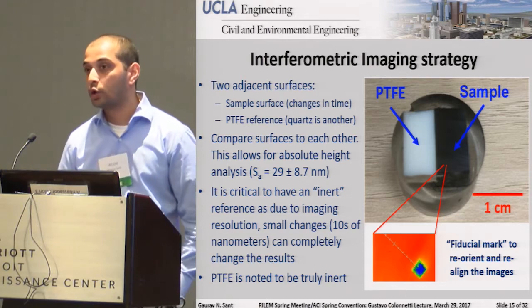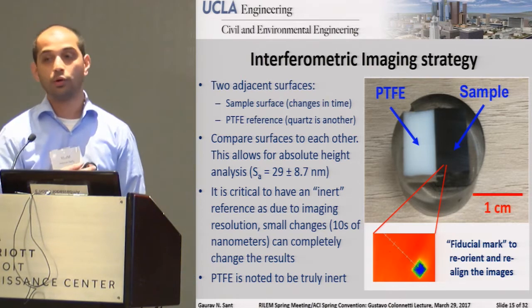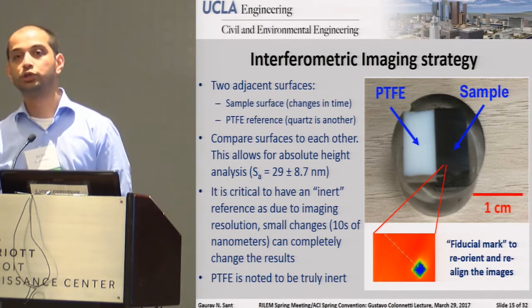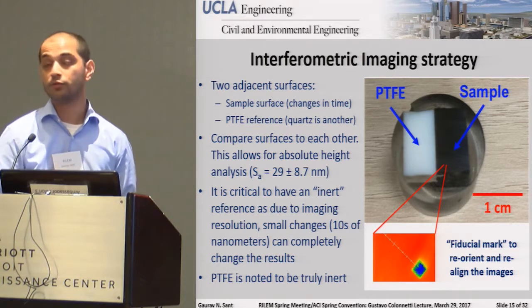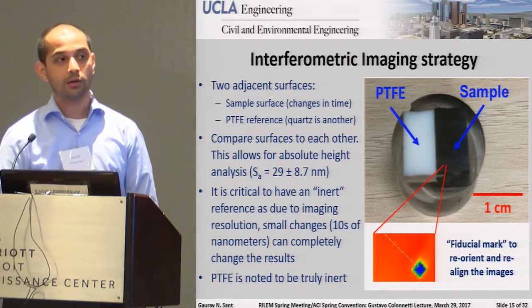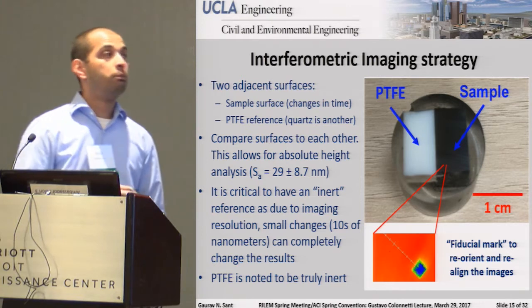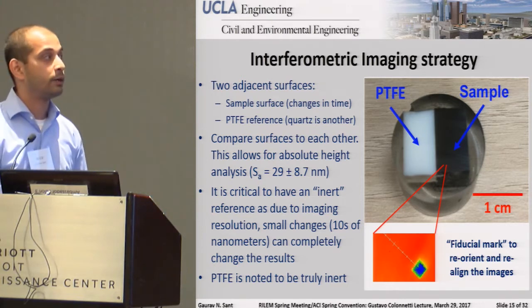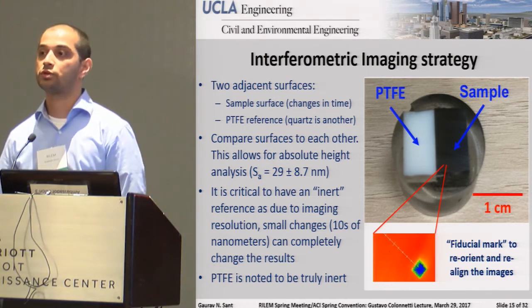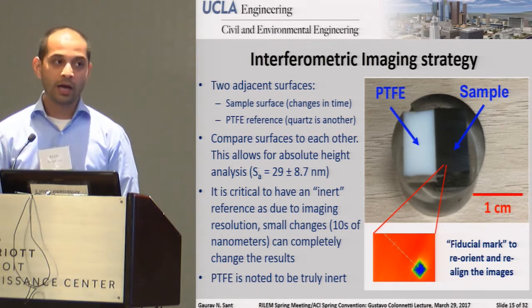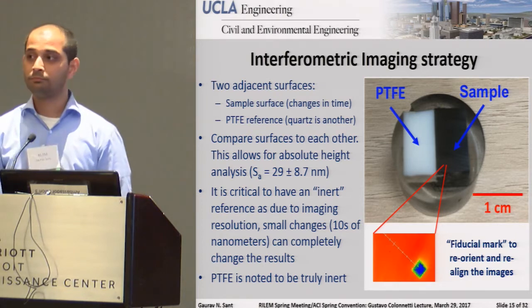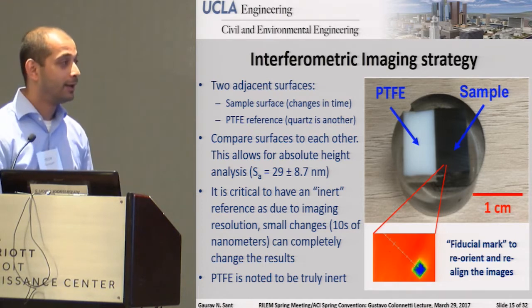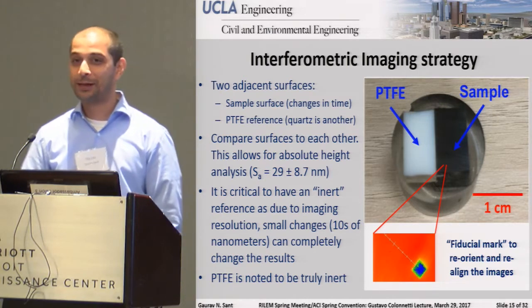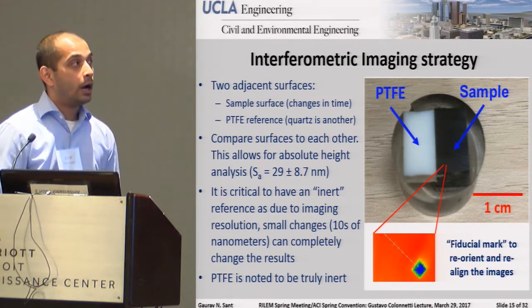Depending upon the systems that you're looking at, if you're looking at something, for example, on the order of a pH 10 type of solution, you can even use quartz. Of course, you want to use synthetic quartz, not things which have inclusions in them. But you really need to be careful about what you're doing, because as you can imagine, if you've got 5 angstroms of resolution, if you don't have an inert reference, you're going to get results which are rather bizarre. And having been through the experience, I'll tell you that that's actually true.